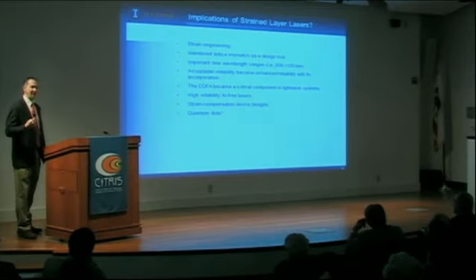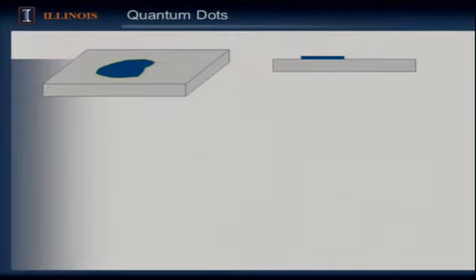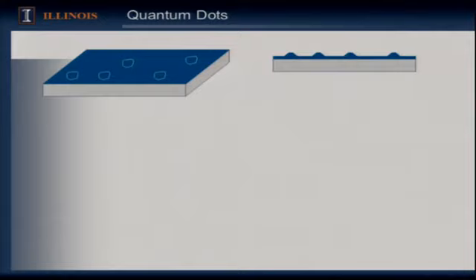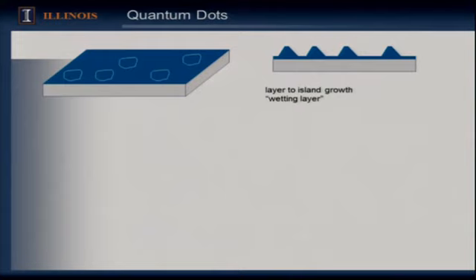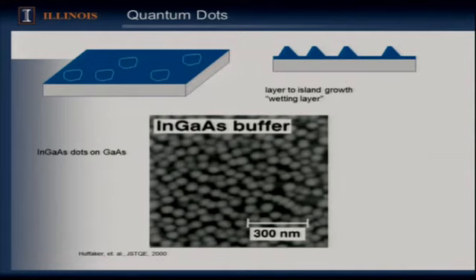It may be a stretch, but I honestly believe that the mindset of getting out of lockstep with lattice match has allowed lots of heterogeneous materials and mixed systems, including quantum dots. Compound semiconductor quantum dots are generally made by growing something that's a two-dimensional strain layer that at some point exceeds the critical thickness and transforms from layer-by-layer two-dimensional growth into three-dimensional island growth — actually most III-V semiconductor quantum dots aren't really dots; they're thin strain layers with bumps from the 2D-to-3D transition, with a so-called wetting layer. A literature search on quantum dots yields something like 80,000 hits.